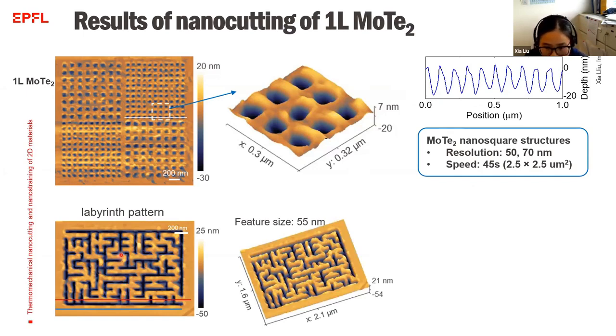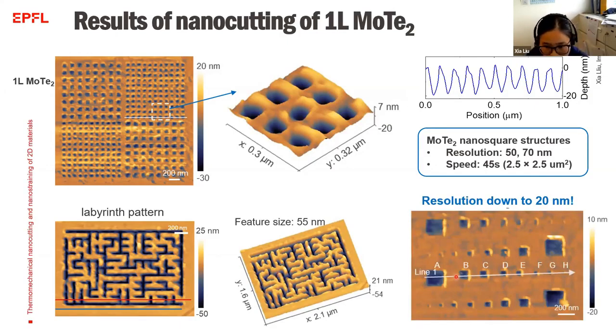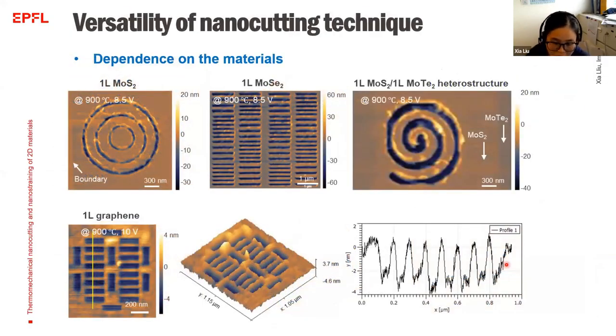From the topography, we can see very sharp cuts are created in the 2D layer. The smallest feature we can get is about 20 nanometers, which is almost the smallest reported for direct writing or direct cutting methods, and is similar to the resolution of e-beam lithography. This is not just applied to monolayer molybdenum ditelluride; it can also be applied to many other 2D materials and many different cutting patterns, such as molybdenum disulfide, MoS2, MoSe2, and also some heterostructures. But currently, this method is not achievable in graphene. From the graph of the indentation, we can see the indentation is about 3 nanometers. So we can see significant strain is increased in the graphene, but not a cut.